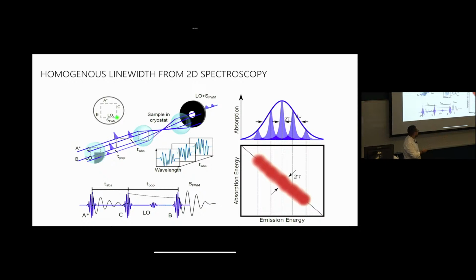But here, I can analyze this 2D line shape to isolate the homogeneous and inhomogeneous contributions, which means that if I can isolate the homogeneous line width, I can tell you what the dephasing dynamics are. I also measure them through the time domain, but I can spectrally tell you what the dephasing time is. And from the dephasing time, I can tell you, now let's change the density so that they're scattering. How does that affect the dephasing? And importantly, how is that dephasing different for XA and XB? And why? How do these phonons that couple to the different excitons, how are they responsible for differences in the scattering rate? And so that's what we're going to try to address here.